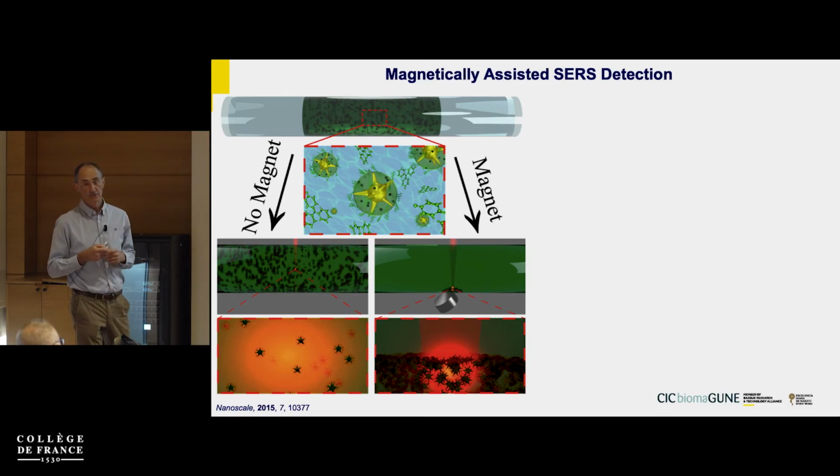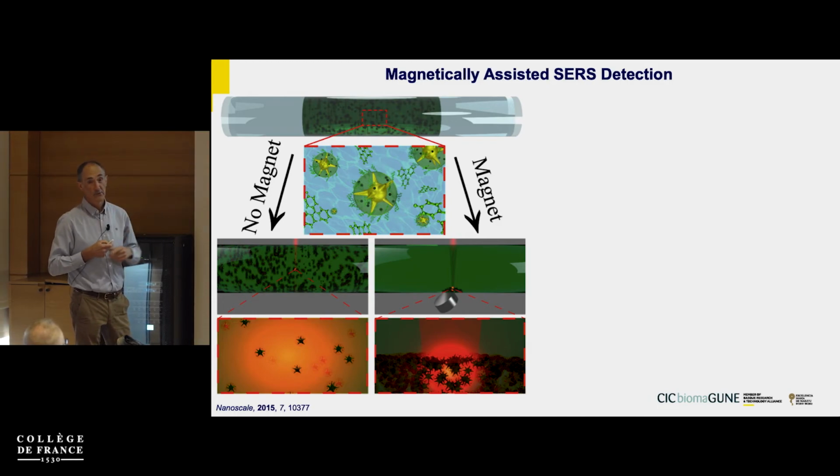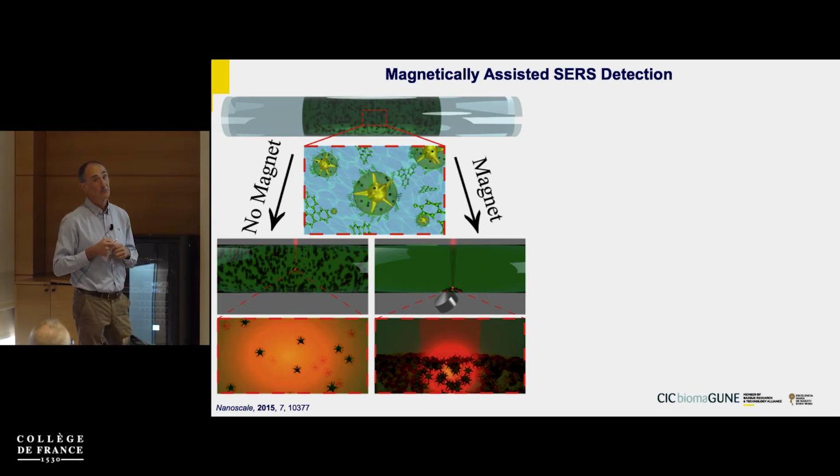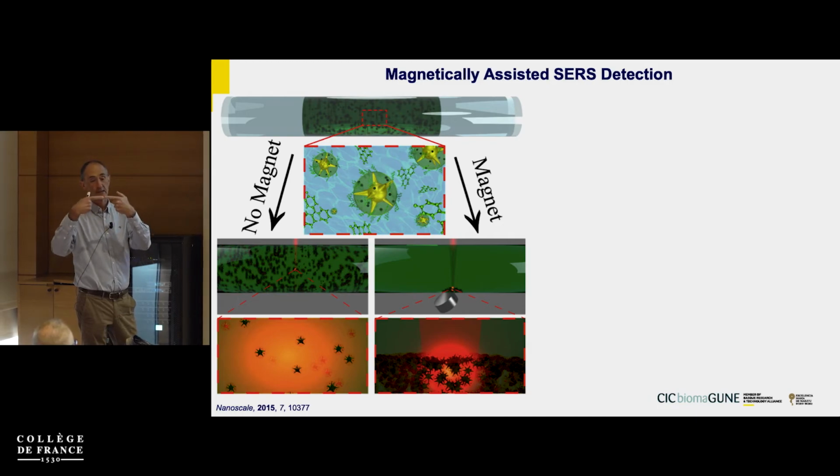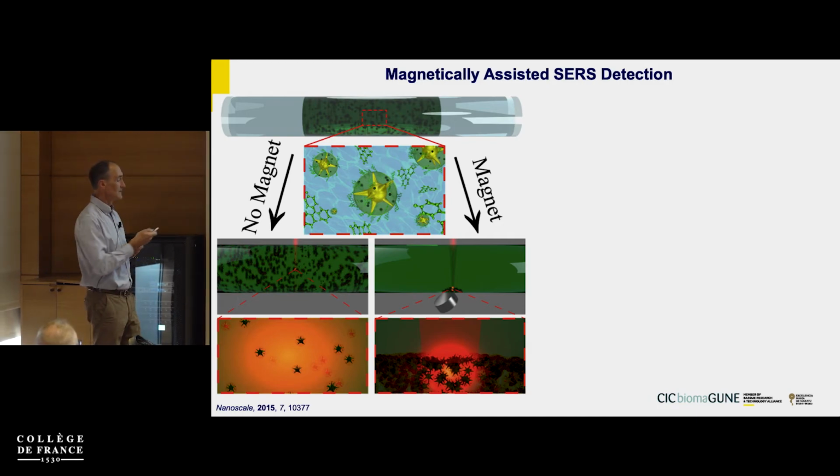And also, you remember I mentioned, I think in the first lecture, that when gold nanostars are aggregating very close to each other, you can have destructive interference and lose the signal. But here they are protected by the polymer shell, so we cannot get this destructive interference. So if any, we can obtain constructive when the tips are coming next to each other.